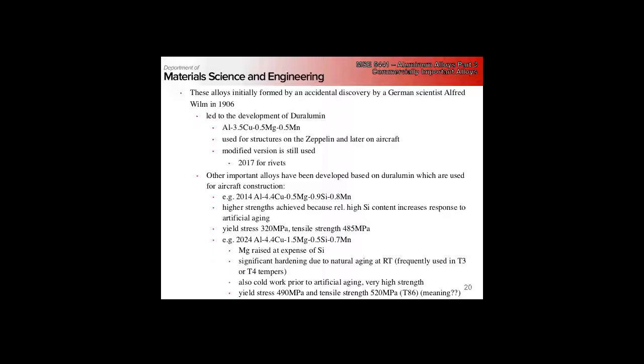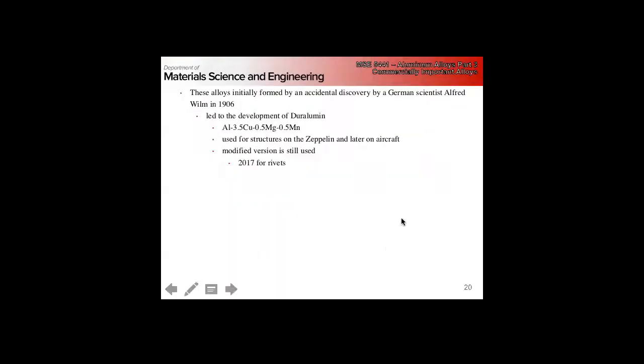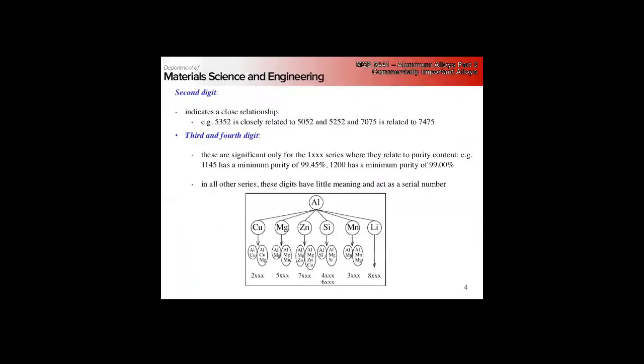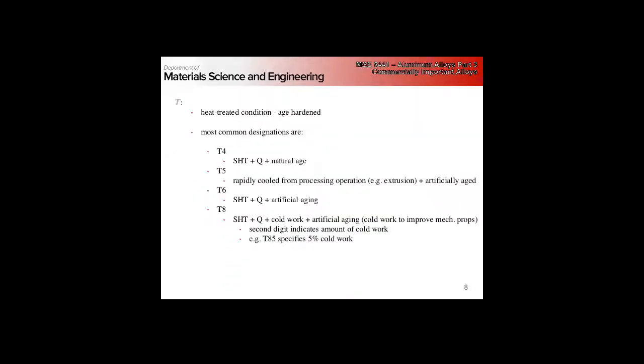Are all these T8s just to stabilize the recrystallization? T8 is just additional work hardening on top of the... so T8, you get mechanical stretching after. So you solution heat treat, quench, cold work, and then artificial age. So T85 is 5% cold work.